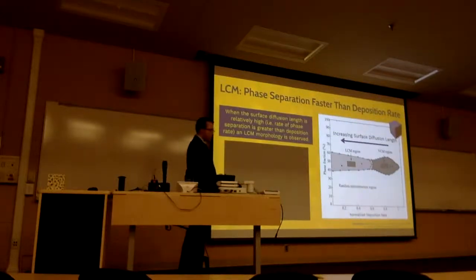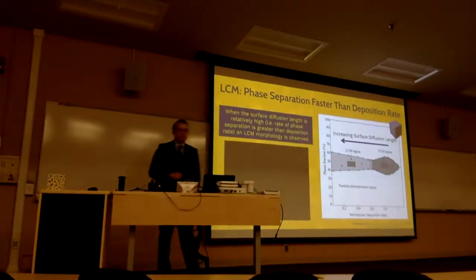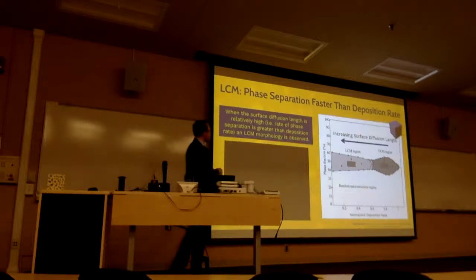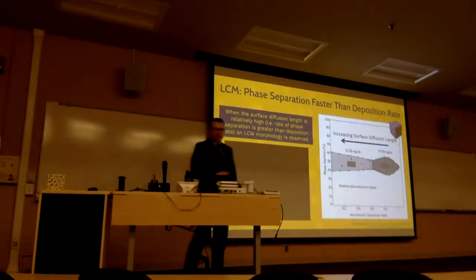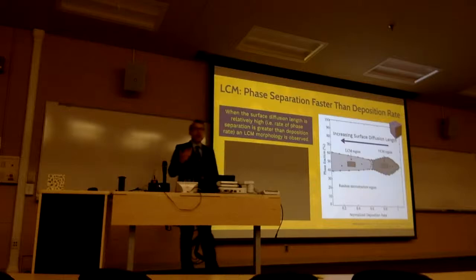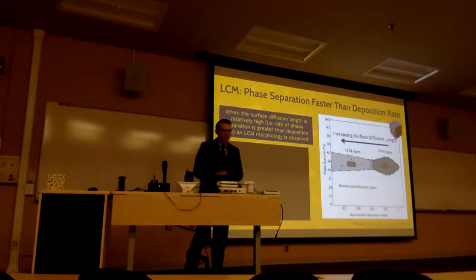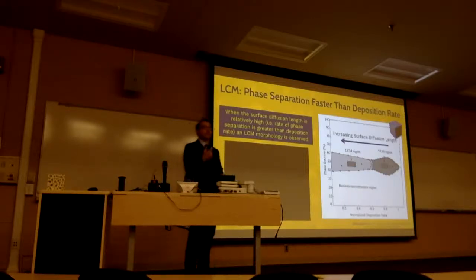And so what I'd like to describe is each of those morphologies in turn and how they develop. So first off is the LCM phase separated morphology, and that is when we have a high surface diffusion length. What's happening here is that the rate of phase separation is much greater than the deposition rate.